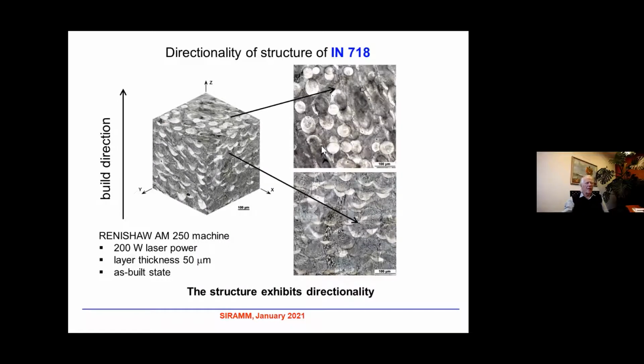How does it look in the case of Inconel? Inconel was produced on a Renishaw machine, another machine. Laser power was 200 watts, layer thickness larger, 50 microns, and it is in as-built state. Again, you can see directionality of microstructure. Here you can see nicely these laser pools, how the laser melted the material. There is also directionality in the build direction, and here at this plane, which is perpendicular to the building direction, you can see again sections through these melting pools. So again the structure exhibits directionality.